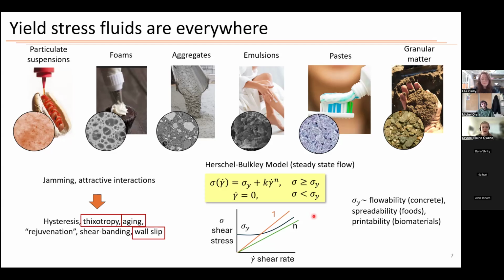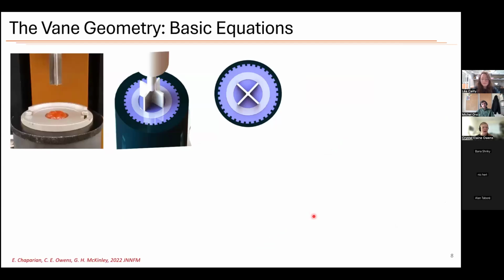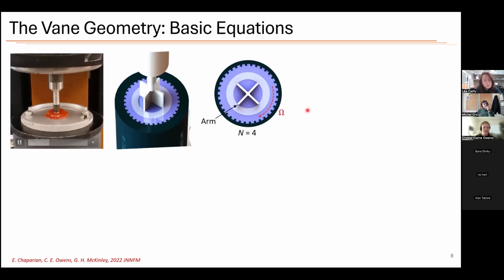And now how we actually make a measurement is when we go into the lab, we go to our rheometer and we will put sample material into a cup or whatever sample holder we have on the rheometer. And then we have, in this case, a vane that we insert into the material. And so this goes in, this rotates, and as it rotates, we will apply a rotation rate, and then we'll measure the resulting torque to get our values. So here, this is a vane that has 4 arms. It rotates, and then it yields some portion of the material, so that you have a radius of the vane, a radius of the cup, and then a radius of the yielded portion of fluid.